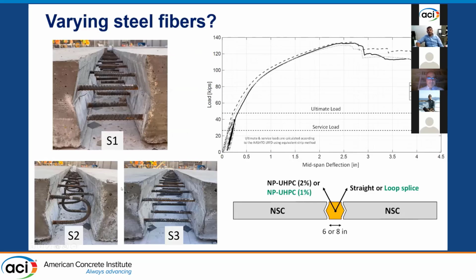So in this example that we did in this testing, using the non-proprietary UHPC, we used 3 different joints for the transverse field joint as a sample here. And we wanted to see if we were to use 1% instead of 2%, from just some back of envelope calculations and stuff like that. We said that, okay, maybe this would come at the cost of increasing the width of the joint a little bit. So instead of the traditional 6-inch width we use for the joint, we went here with 8 inches. Not really a big difference, but we wanted to make sure that at least for 1% we have a little bit more lap length. And we wanted to test the 2 of them.